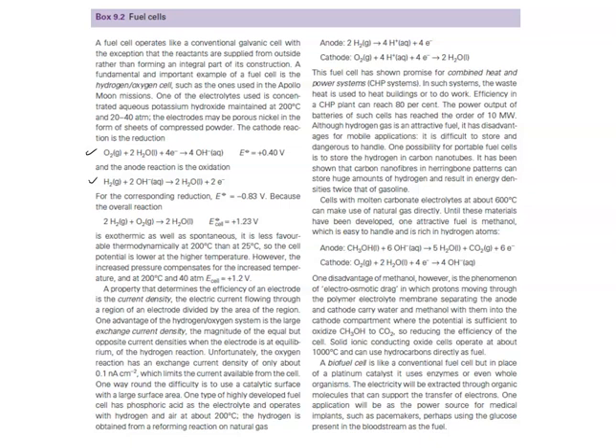Because the overall reaction, two hydrogens plus oxygen yield water, has a standard potential of positive 1.23 volts, it is exothermic as well as spontaneous. It's less favorable thermodynamically at 200 Celsius than at 25 degrees Celsius, so the cell potential is lower at the higher temperature. However, the increased pressure compensates for the increased temperature, and at 200 degrees Celsius and 40 atmospheres, the potential for the cell is positive 1.2 volts.